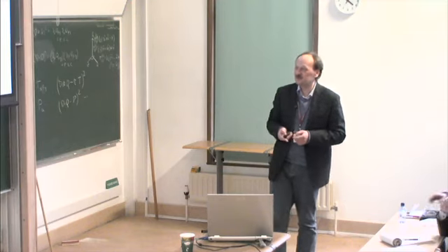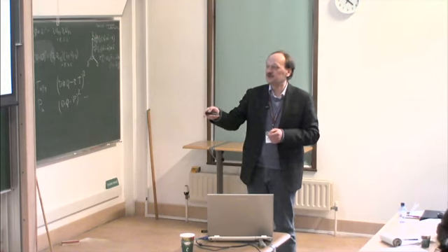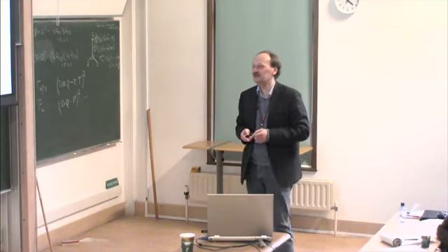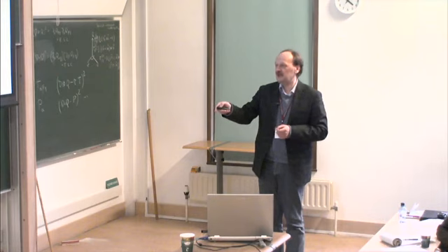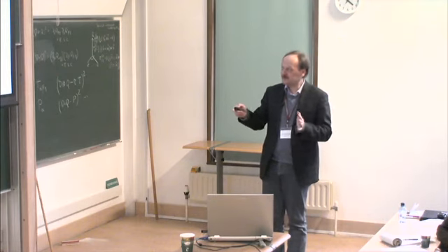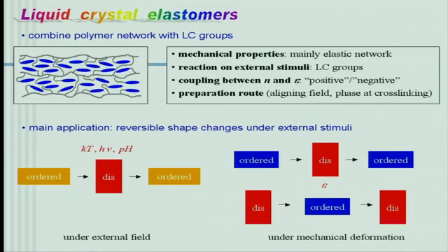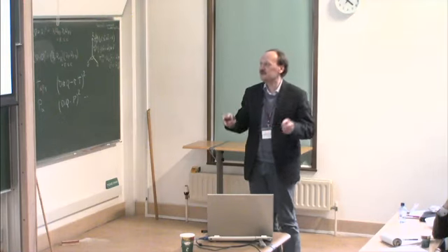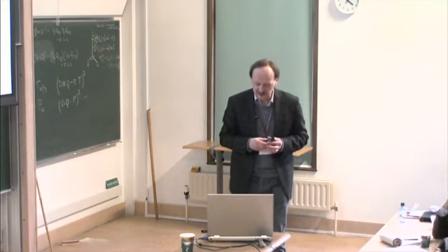But when we remove the external perturbation, the system reversibly returns to the previous state. And vice versa, if we affect mechanically the backbones or the polymer matrix in general, then we can also see transitions like stress-induced destruction of the liquid crystalline order, or stress-induced induction of the liquid crystalline order. And again, when the stress is removed, we get back to the original state.